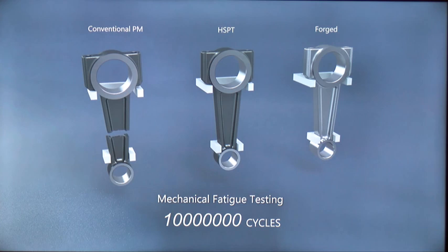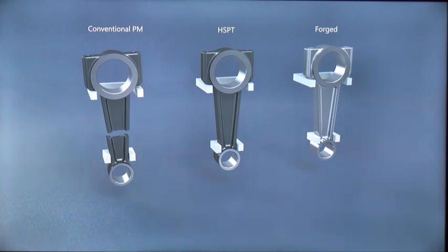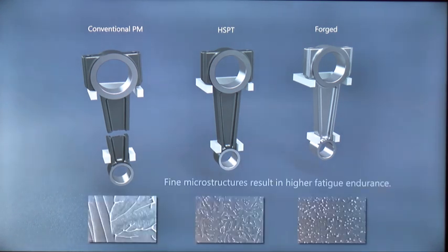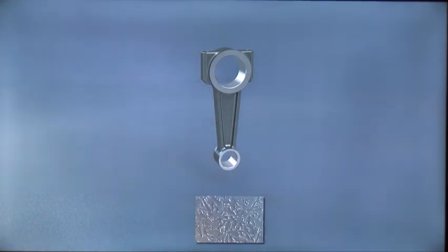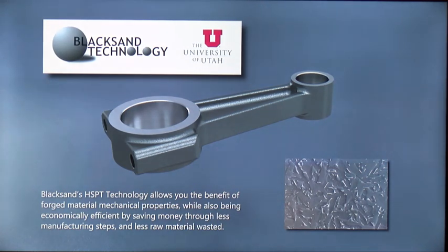You can see our materials are very competitive with forged materials, so they undergo fatigue mechanical testing a lot further. You can see that picture on the bottom just showing the general sizes. There's a massive discrepancy as far as how that would go. So as you can see, ours finds kind of a sweet spot of the advantage of near-net shaped parts while also keeping high strength, which was previously not being able to be done. So you get less material wasted, but you can have a higher strength.